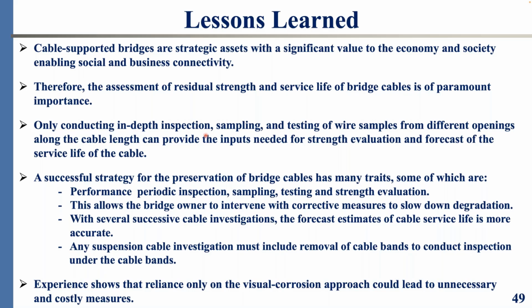A successful strategy for the preservation of bridge cables is a whole discussion, but some of the traits of a good preservation strategy are to perform periodic inspection, sampling, testing, and strength evaluation, because this will allow the bridge owner to intervene at the proper time with corrective measures to slow down degradation and to stay ahead of degradation. That is really key. And with several successive cable investigations along the service life of the bridge, the forecast estimate is honed, and you can get a more accurate assessment of the forecast. And any suspension cable investigation, from our experience, must include removal of the cable bands to examine the cable wires under the cable bands. This is one of the areas that are vulnerable to degradation.